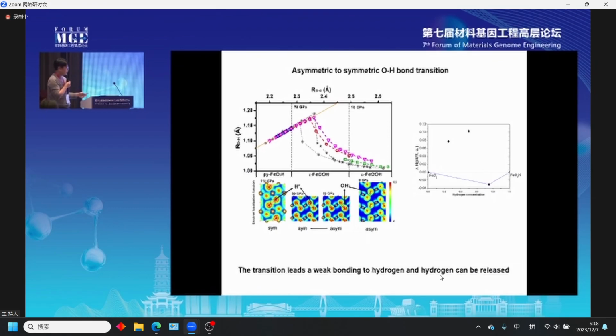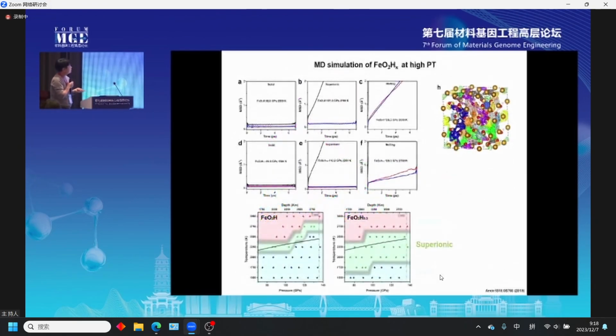diffused through the space. So we conducted ab initio MD simulation, and we found that there is a partially melting state only. While iron and oxygen vibrate harmonically over time, only hydrogen starts diffusing. So this is a superionic state. Only this proton diffusion is happening here. So this is the MD result.